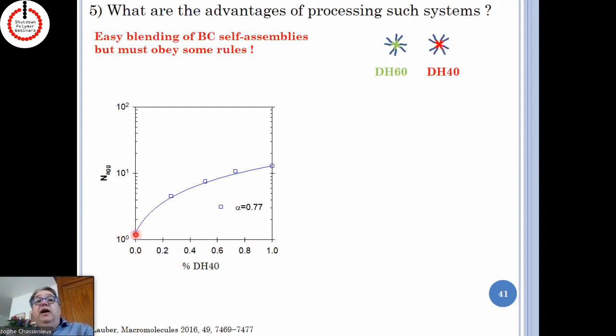So here you have a system, this polymer, at this ionization degree, forms no micelles at all. The same polymer with less acrylic acid inside the hydrophobic block has a tendency to form micelles with an aggregation number almost equal to 10.